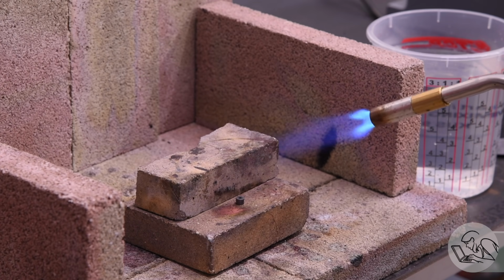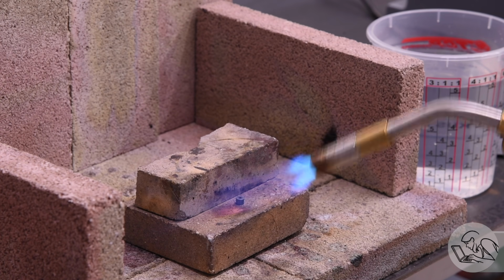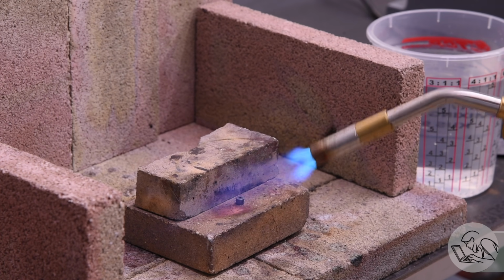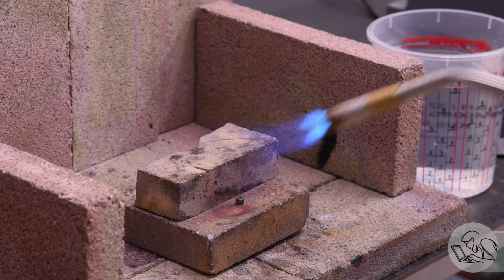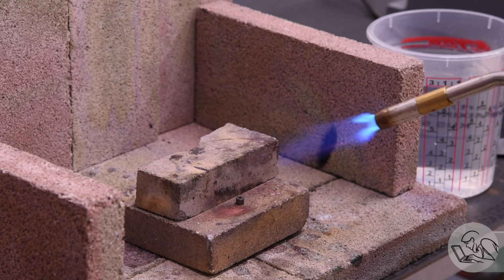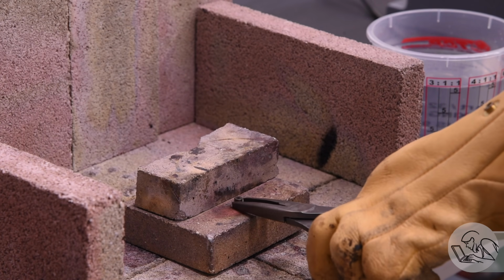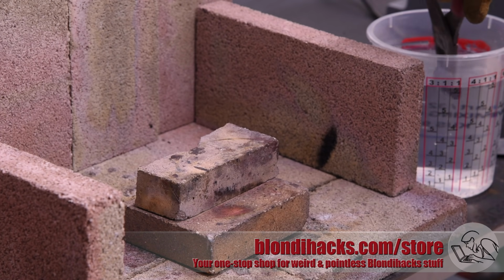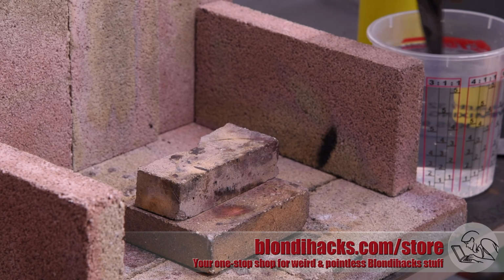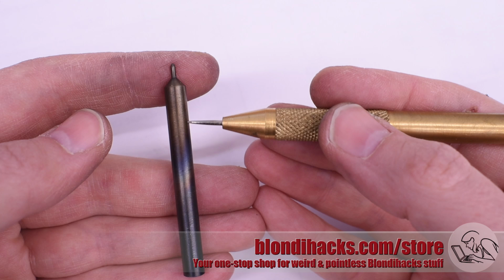The process is the same for the die, but because I don't have that long length, I have to kind of just kiss it with the torch and wait a minute, and then hit it again and wait, and just watch that color develop in it, and again, try to stop on that light yellow color. Here's the final temper. Now, I ended up with more of a brown than a yellow on the end, so this is probably a little bit over-tempered, but we're going to try it anyway.